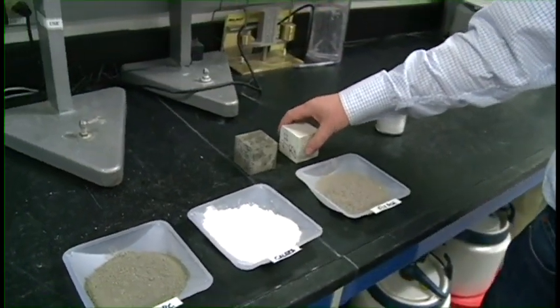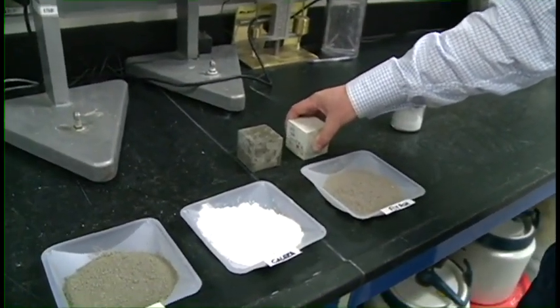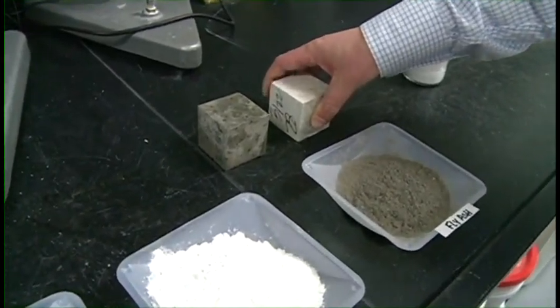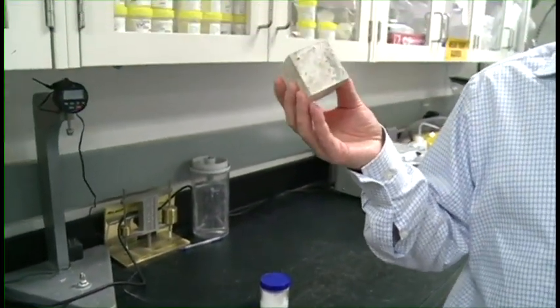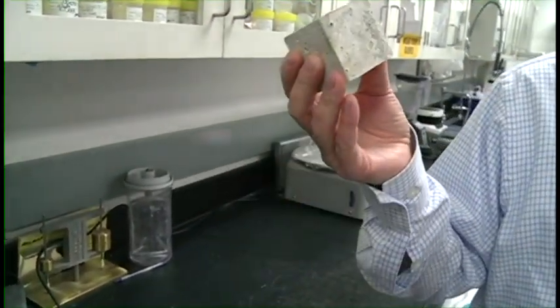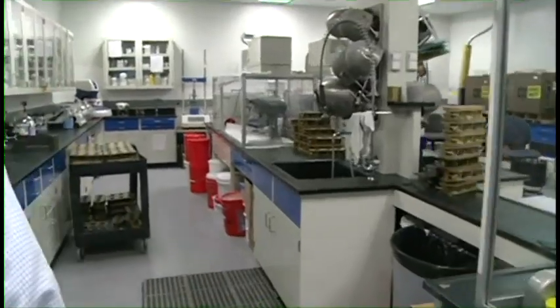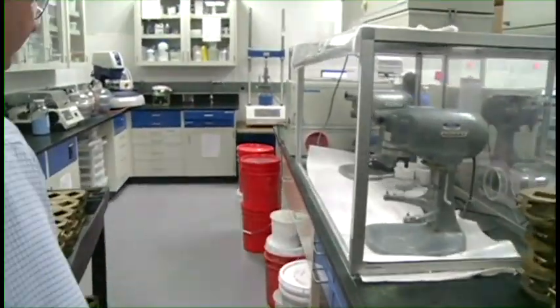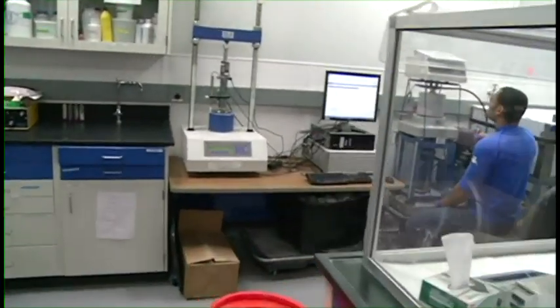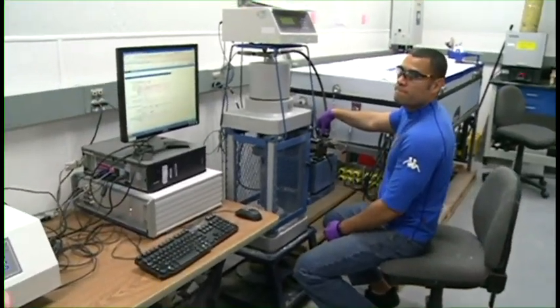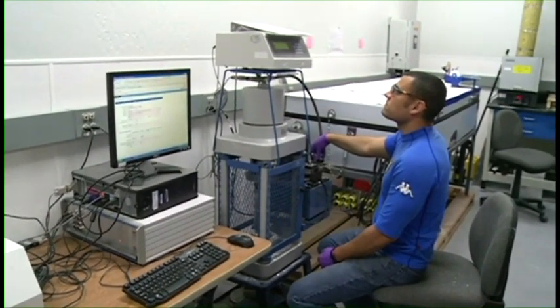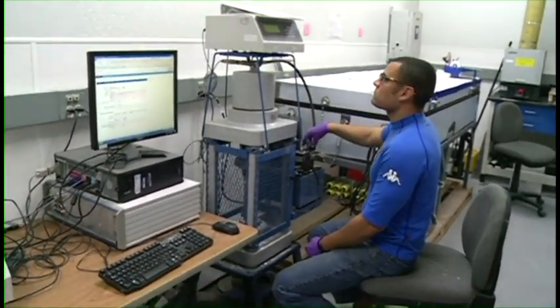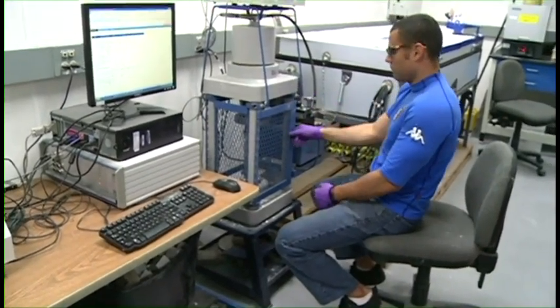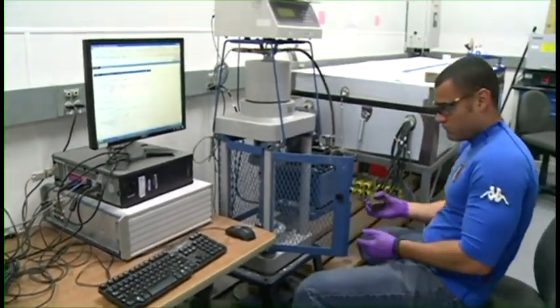We need to test these materials according to strict industry standards, and we follow a lot of ASTM testing protocols. You can now see that this is a mortar cube that contains a percentage, in this case maybe up to 20%, of the Calera calcium carbonate, which contains embodied CO2. In this laboratory, we test these materials, for example, for their compressive strength, which is one of the characteristics we're interested in. With this particular apparatus, we're testing the compressive strength of that cube that we formed using our material. And what we want to show is that the material conforms to the industry specification. In this particular case, it's related to the compressive strength.